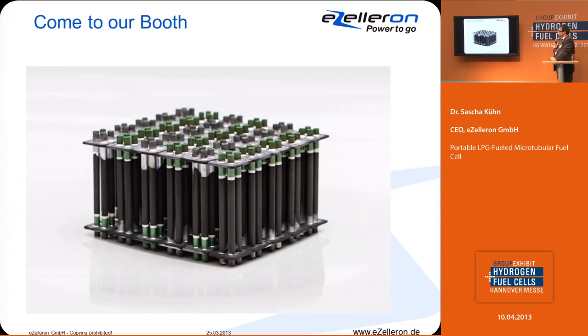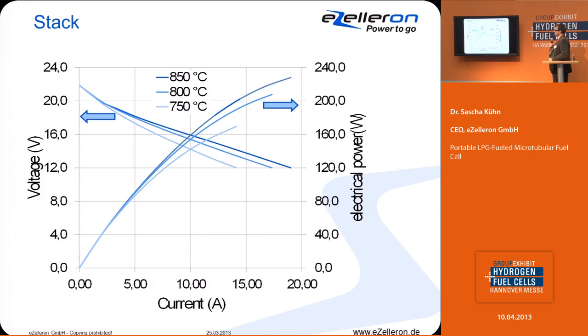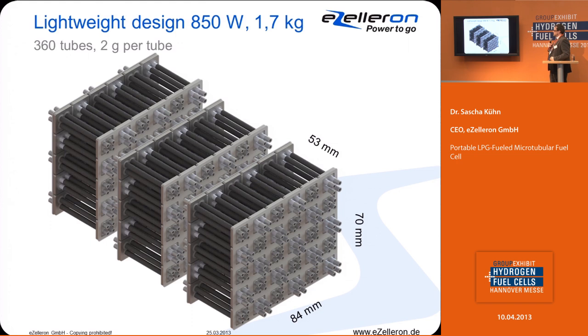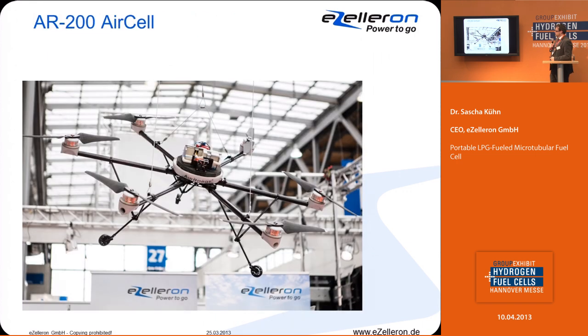So we operate with LPG. This is our 200 watt stack. You can see that at our booth, B50 here in this hall. The stack is at about 200 watt at typical values of 0.7 volts, 850 degrees C. And in the next step, we want to integrate several of these stacks into a bigger stack unit, which we need for a flying object that you also can see at our booth.